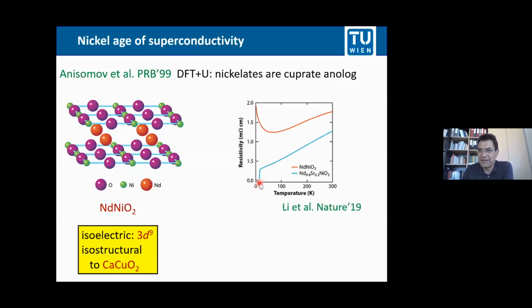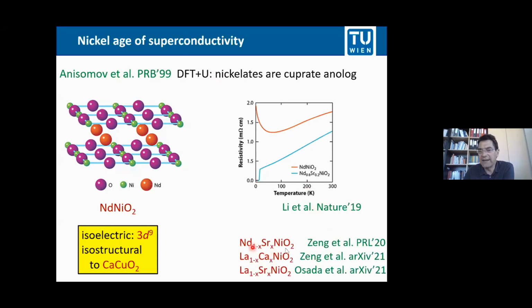For us theoreticians, it's maybe not so surprising, because 20 years earlier, Anisimov, Rice, and a co-worker actually discussed that nickelates are an analog of the cuprates, and therefore we should expect superconductivity in these systems. It's maybe more surprising that it took so long, namely 20 years, to synthesize these materials, and it even took one year before the next group, the group of Ariando from Singapore, was able to reproduce these results. Just to recall, for the cuprates, it was only a matter of a few months to reproduce the results. For the nickelates, it took one year. That shows again how difficult it is to make these systems.